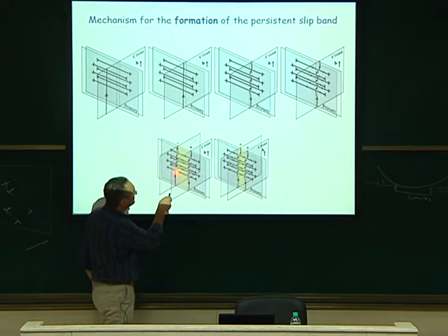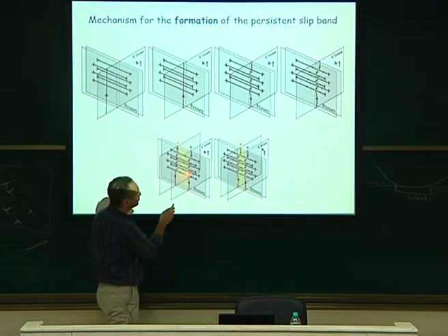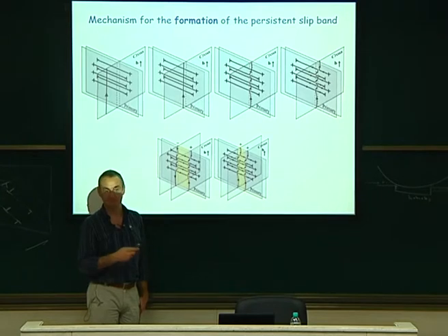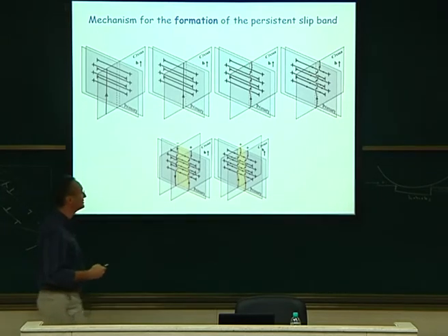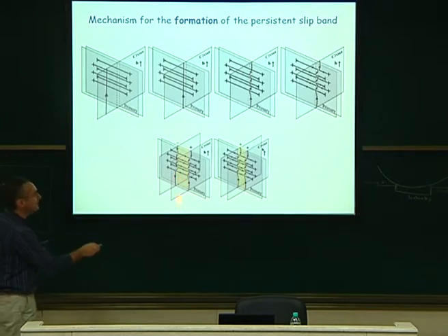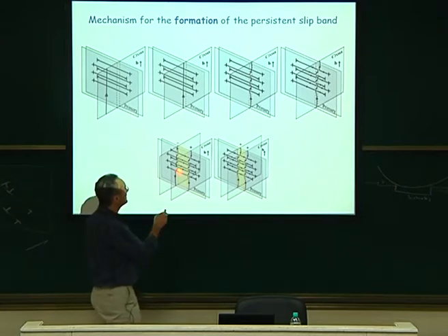You will see that it will lead to these small guys here, for which the Burgers vector is here, and these are the loops. What are those loops? Prismatic loops. You see, I love those guys. They are everywhere, these prismatic loops. These prismatic loops can glide in the yellow cylinder. They can glide easily, as we saw last time, okay? So these are prismatic loops.